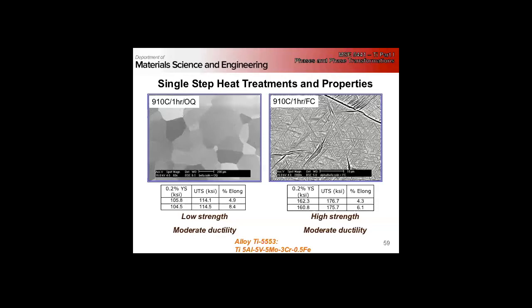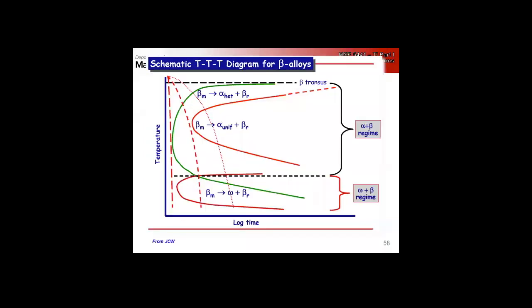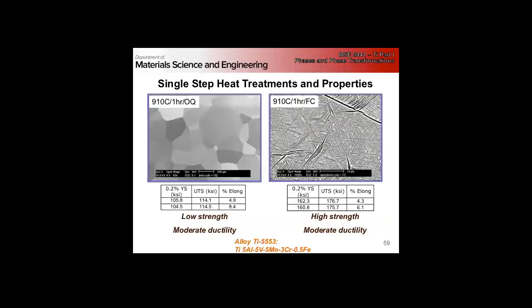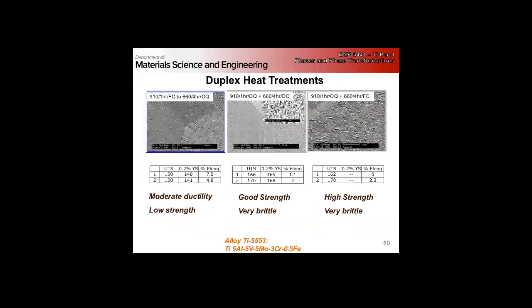The one on the left was omega. Because 5553 is the alloy we were talking about where we oil quench, we came down into the omega region. So in this structure, we're going to have a fine omega dispersion. Aging for an hour, this is furnace cooled, we get a basket weave structure. We're going to have higher strength, but similar ductility.